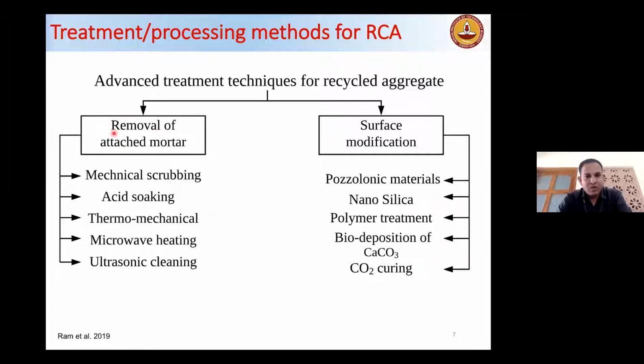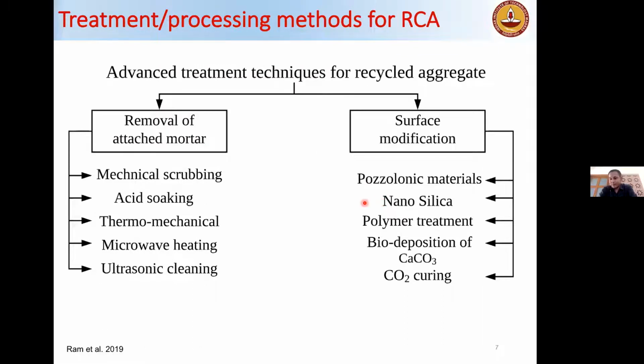So removal of attached mortar could be done by mechanical scrubbing and acid soaking and combined action of thermal and mechanical action. And there is also microwave heating, and there are other methods like ultrasonic cleaning. And surface modification could be done by coating with pozzolanic materials and impregnation of nanosilica or nanolime. And there are other methods which are polymeric treatment. So you basically coat the aggregate surface with PVA and other chemicals to increase the bond or to reduce the water absorption. And there are biodeposition of calcium carbonate and curing or carbon conditioning.